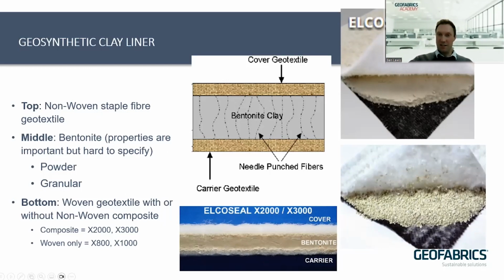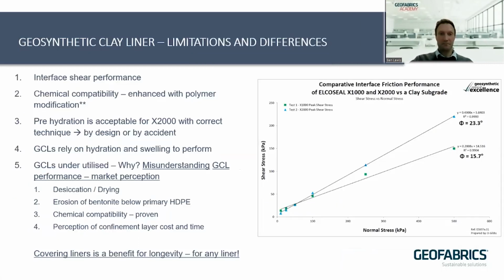On this picture, you can see the black woven. There is a black woven in this bottom one as well, but the X2000 and X3000 have that secondary or tertiary geotextile needled on the underside. And that is important because it does have impacts on interface performance, interface shear performance, puncture resistance, and even the ability to control the swelling in rainfall events.